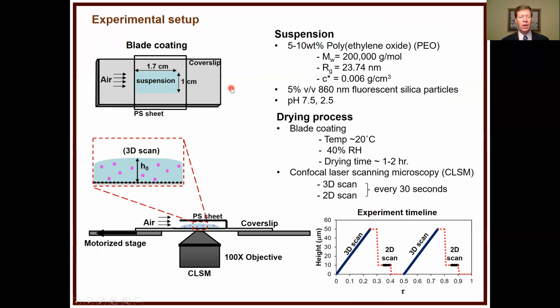And so the setup is really simple. We're not going to look at roll-to-roll coatings, but we could certainly, if I was handed a sample of a roll-to-roll coating, hot off the press, or just as it was coated, and then put it on the microscope, and then perform a drying operation that's similar to that in industry. We certainly can do that. Right now, all I'm going to do is just blade coat a suspension, and this material is going to be covered so that the drying is mostly unidirectional, which is more similar to what happens in roll-to-roll processing conditions. And then we're going to scan through the system, and I'll talk about that in a second. The constituents are similar to what they use in the pharmaceutical industry.